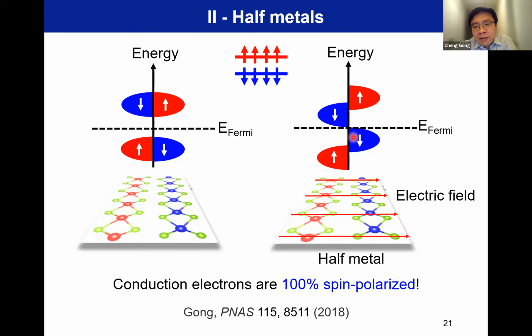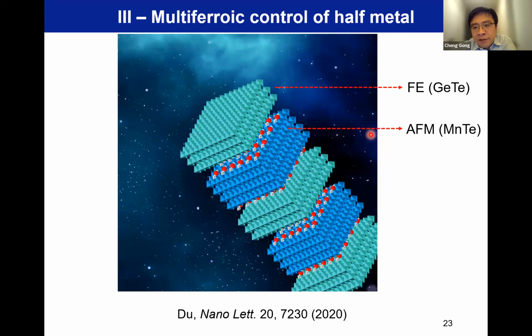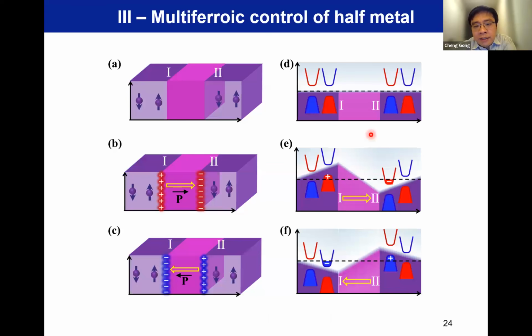So that's why we move on to the third piece of work by including ferroelectric materials. We are not only applying the external electric field, but the ferroelectric polarization can help you, because the ferroelectric material with the inherent polarization can enlarge this field effect. With that, we hope to use a relatively small voltage to reach the half metallic state.